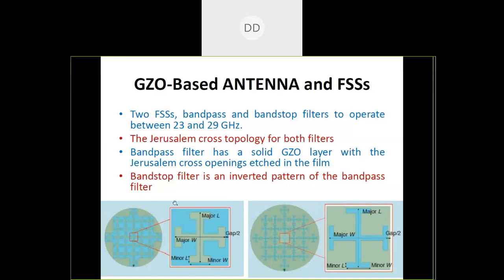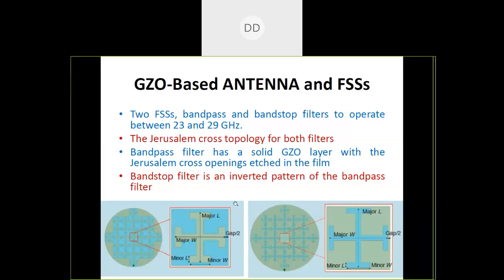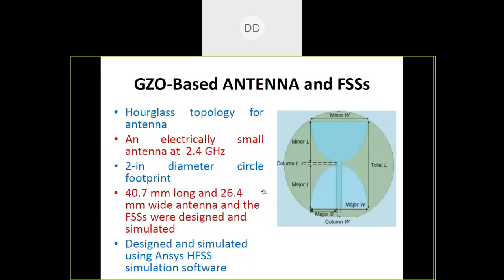In the band pass filter, on this side, we can see that we have a solid gallium doped zinc oxide layer with the Jerusalem cross opening etched in the film. These are the openings, and this shows the film. Similarly, on this side is the band stop filter. We can see that the pattern has been inverted. In place of the film, now we have a slot, and where we had the slot, we now have the film pattern. So this resulted in two different frequency selective surfaces.